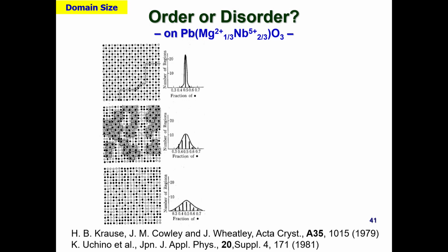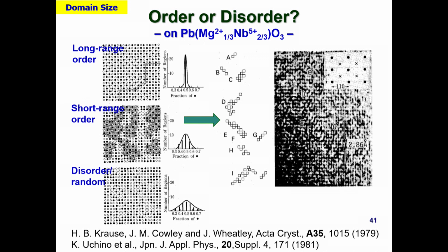This is a computer simulation. At that time, we didn't have beautiful computers, so we needed a long time to calculate only this. So short-range order and long-range order and disordered, or the ordering parameter was changed and the computer simulated. In that case, you can easily find this: the ordered structure surrounded by the disordered structure. So an ordered island seems to be created.